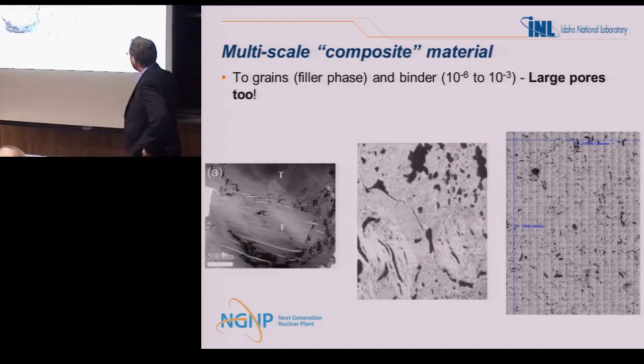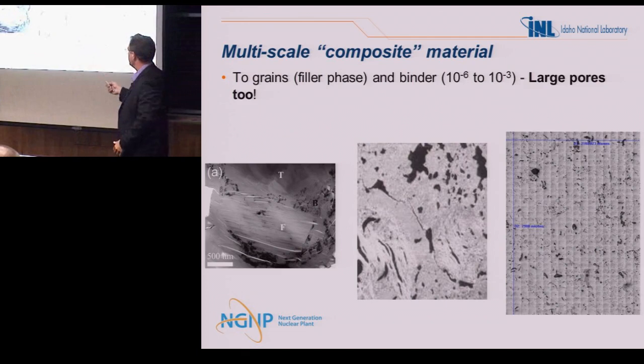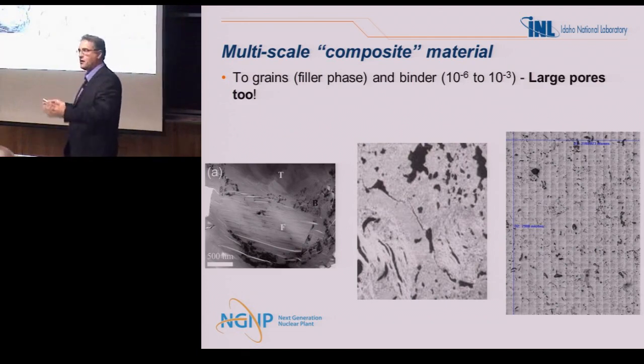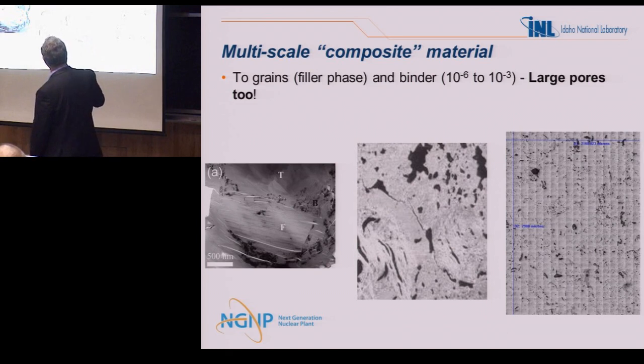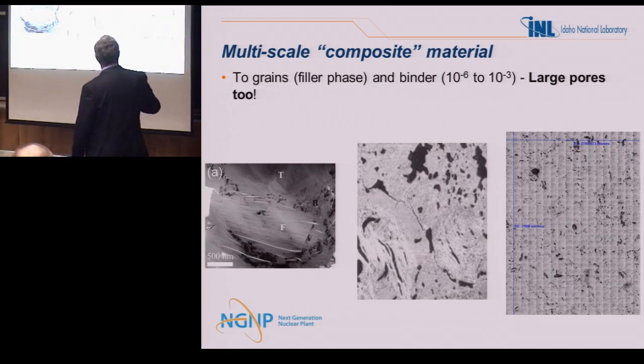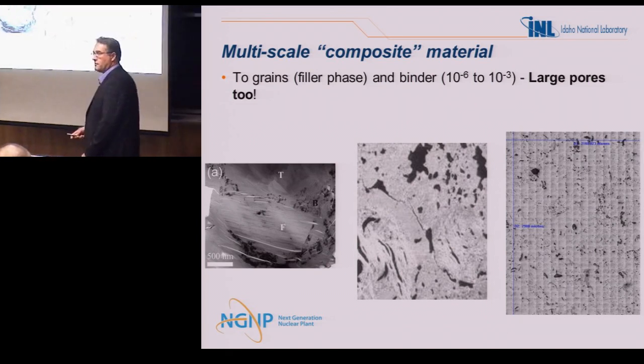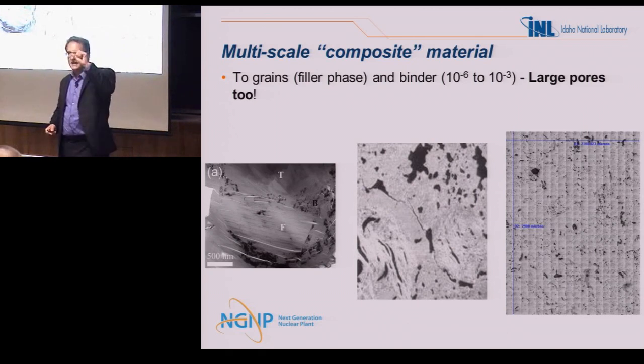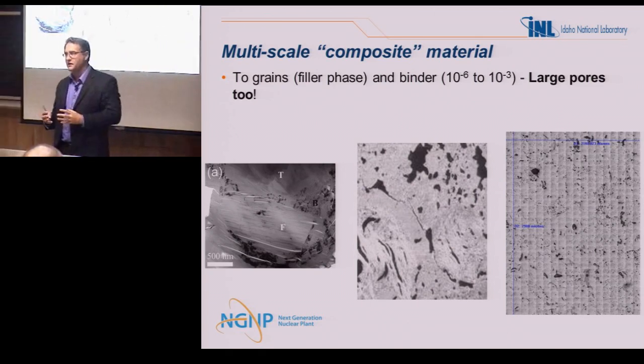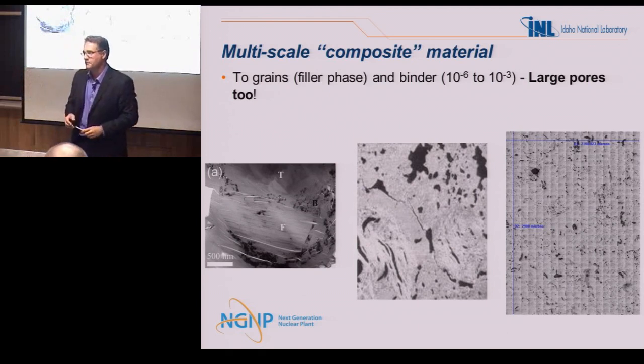Now we move up to the next length scale. These filler materials, the cake flour that I was talking about, turbostratic. And then you have these filler materials with this binder phase, the pitch that I was talking about. And look what you got here. Huge gas entrainment pores. And then finally you start looking at the greater microstructure. Remember, it's anisotropic at the crystallite level. It's isotropic when we grind it all up and we put it back into the cake batter. The macroscopic response is isotropic.